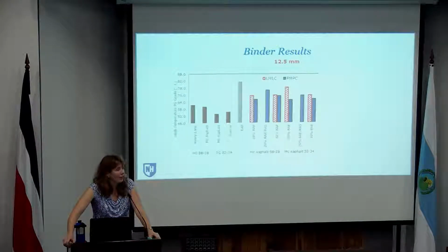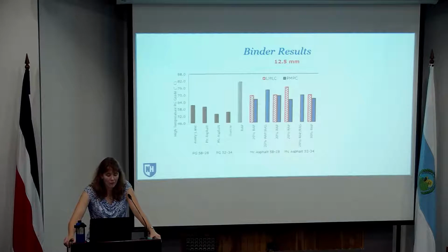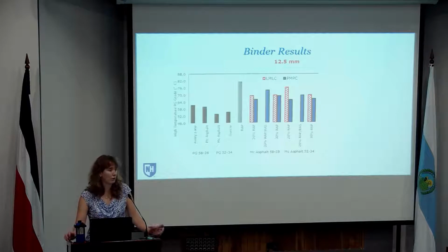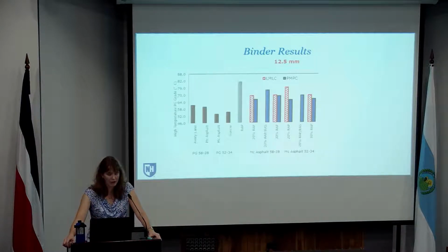Now looking at the extracted and recovered binder results. What I'm showing here is the results from the 12.5 millimeter mixtures. The bars that are in red, those are the laboratory produced mixtures. The bars that are in blue, those are the plant produced mixtures. So again, the difference between the two, the laboratory produced mixtures were all mixed and compacted in the laboratory setting. Plant-produced mixtures were sampled after plant production, and then the extractions and recoveries done.